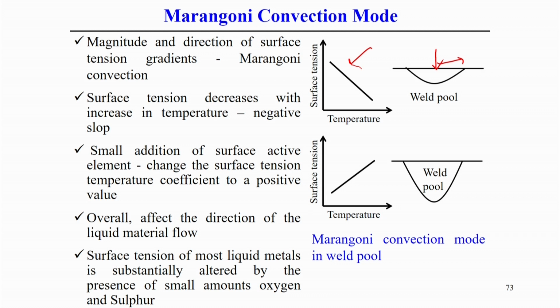But what happens if a small amount of surface active elements is added? That changes the surface tension temperature coefficient to a positive value. So, adding surface active elements changes the slope from negative to positive. When there is a change of the slope, the typical nature of the surface tension gradient impacts the nature of the material flow. So, in the second case, the gradient changes from negative to positive, and accordingly the shape of the weld pool changes. The weld pool becomes narrower in width, but the depth increases.